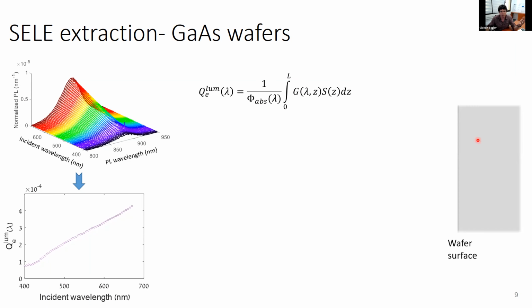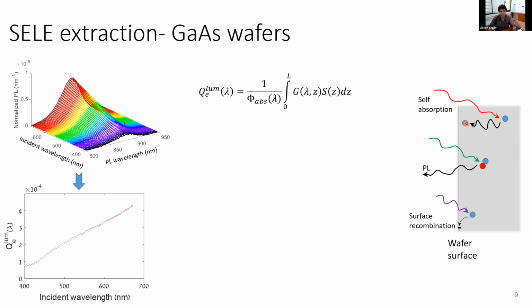So we have here a cross-section of a gallium arsenide wafer, and this is where the surface is. And if carriers are generated some distance from the surface, there's a chance that they will recombine radiatively and emit a photon in the process that we call photoluminescence. However, if this optical generation is happening deeper inside the device, this radiative recombination photon can be reabsorbed somewhere inside the wafer, which is what we call self-absorption. And if the optical generation is happening very close to the surface, there's a higher chance for surface recombination. So once again, we will not measure PL in this case. So putting all this together, we expect that near the surface, the SELE will be fairly low. It will increase as we move away from the surface and then decay as we move deeper and deeper inside the material.